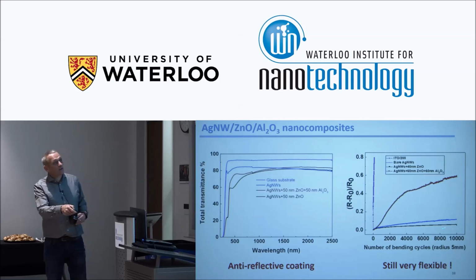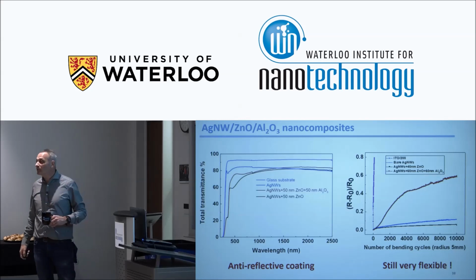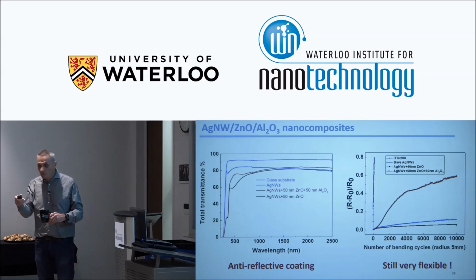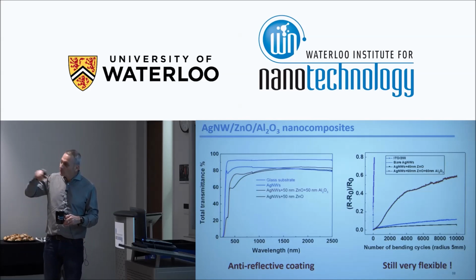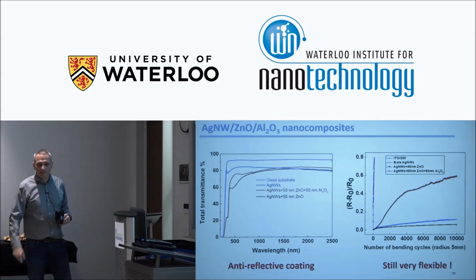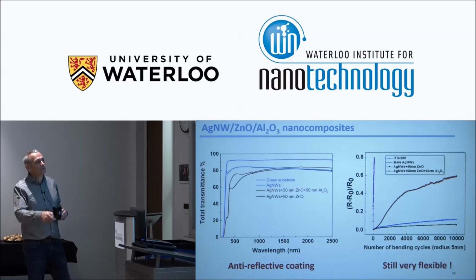Why is this one lower than that? It's probably because we are enhancing the adhesion of the layer as well. Okay, you have some silver nanowires, and then you put an oxide, and if the oxide has a kind of envelope, and if the oxide is happy to adhere to the substrate, that can help as well to have less delamination when we are bending them.